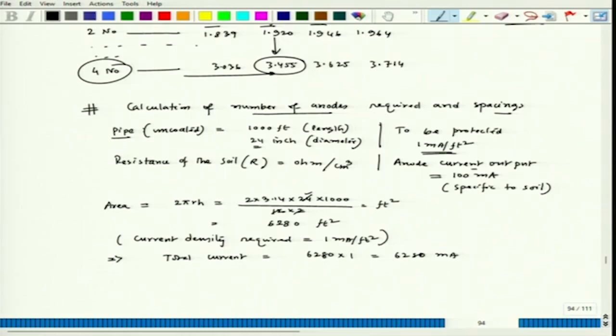Now we know the anode current output, so that has been calculated by using that formula. If it is a magnesium anode, then it is 15000 F y divided by rho. This is I_MG when the pipe is bare. The magnesium is never coated, it is the pipe that is coated. And in the coated case, this value would become 120000. Now those F and Y we can find out from those tables as we have discussed before coming to this part. Now this is the total current that will be required for protection when we need to supply this much current density.